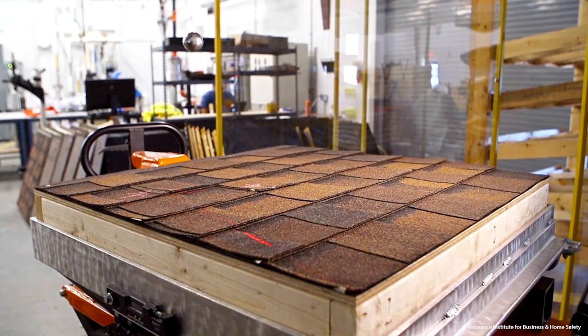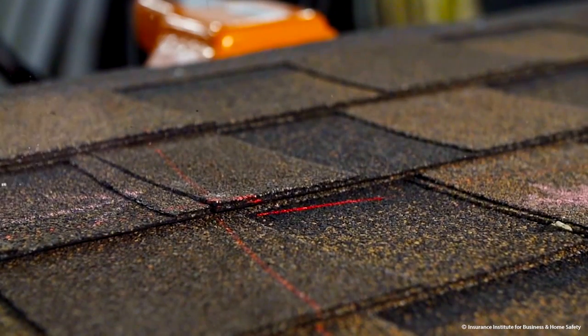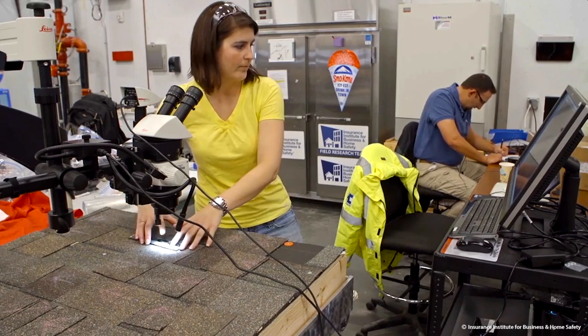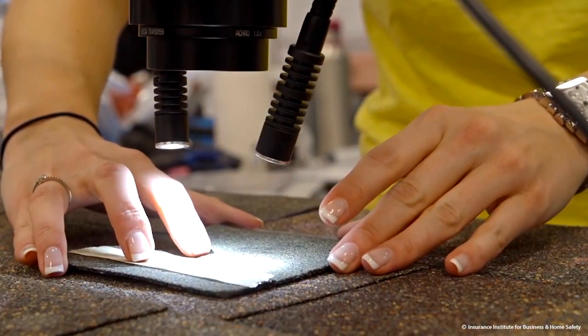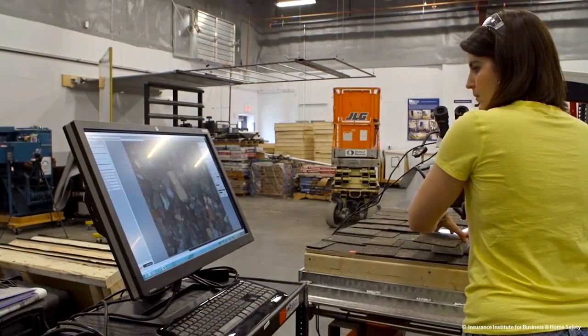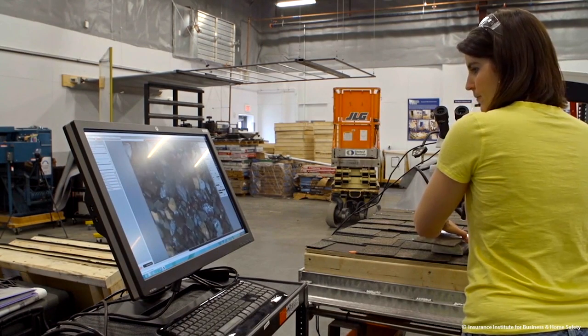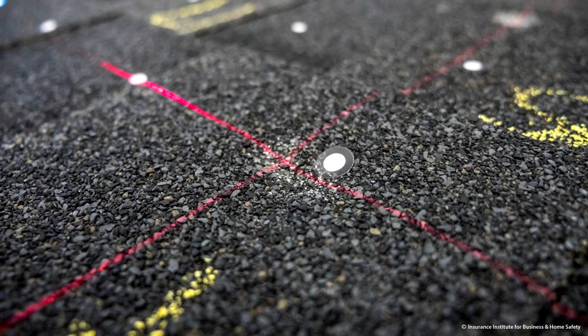And so for the test method, this steel ball is dropped 2 consecutive times in the same spot. And if that shingle is inspected under a microscope and then bent over a mandrel and there's no crack visible, that passes as an impact rated shingle, right? If it doesn't, if there is a crack, then it does not pass. A couple things about UL 2218, I want to note 2 discrepancies with the test method. First discrepancy, it completely misses one of the most important damage modes we see in hailstorms, and that's granule loss on these shingles. And so you can see the granules covering that shingle.